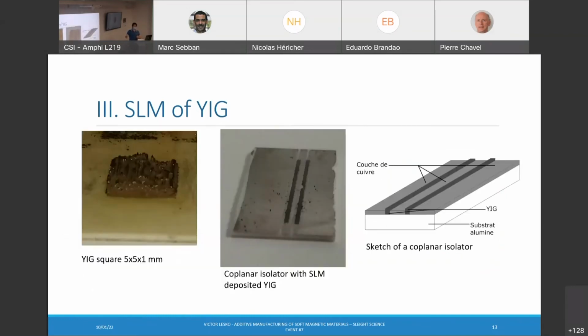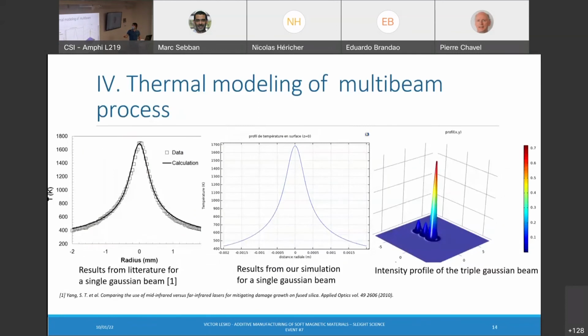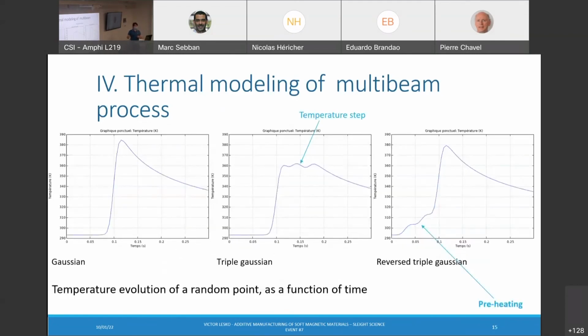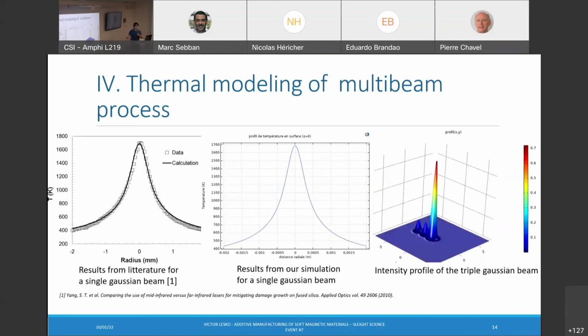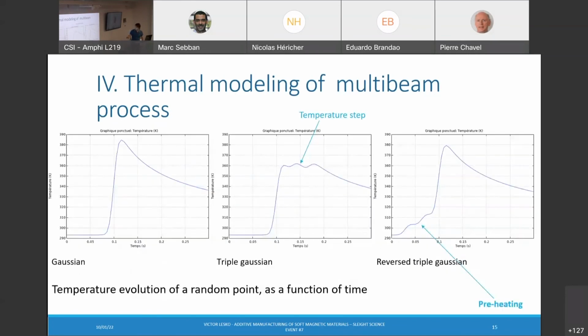These are the results we got. This is a square of YIG of 1 millimeter height. And this is a coplanar isolator. We also made some thermal modeling. This is a simulation for a silica glass sample, but it can also work with our powder. This shows that we can reach a temperature step by doing multibeam processing. We can also do some preheating, and the temperature step allows us to avoid a peak temperature.